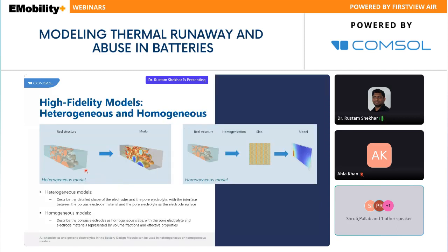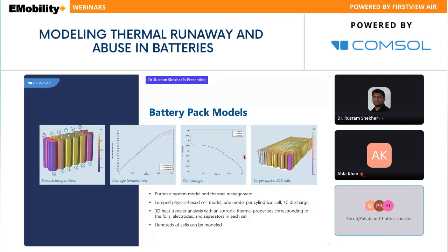So now we talked about the different approaches. Then the two different approaches, or the three approaches, can be compared, and then you can see how that can be handled in COMSOL Multiphysics. So here what we observe is that we have one heterogeneous model, which has the detailed shape, and the electrode and pores, electrolyte, everything is accommodated there. And there's a model which is homogenized, which accounts for the homogenized slab. So we can just take the real structure, make a model of it, and then this real structure can be converted to a slab, which is the homogenized phase, and create a model out of it. So when we compare these two approaches, heterogeneous and homogeneous, they can give you the same results, but they may have different kinds of outcomes when it comes to comparing both approaches.